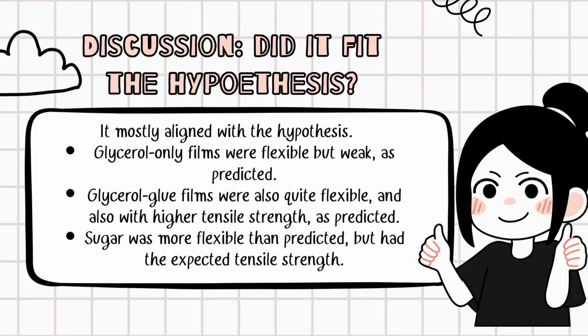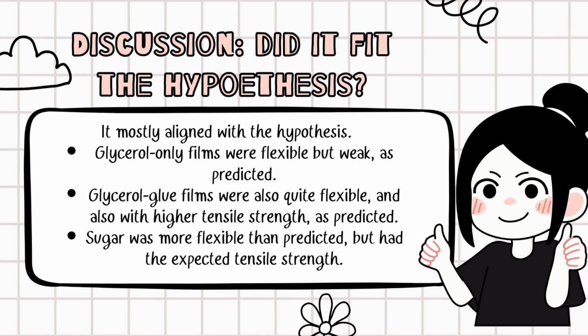The data collected mostly aligned with the hypothesis. Glycerol-only films were highly flexible but weak, supporting the idea that glycerol disrupts hydrogen bonding between starch chains, increasing flexibility but reducing tensile strength. Glycerol glue samples maintained a similar flexibility but with improved strength, likely due to the PVA forming extra hydrogen bonds that stabilize the polymer matrix, matching the predicted range of tensile strength.